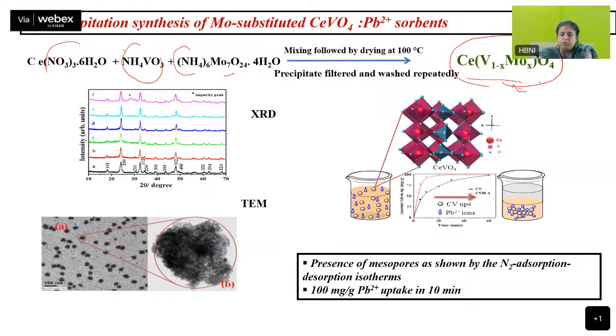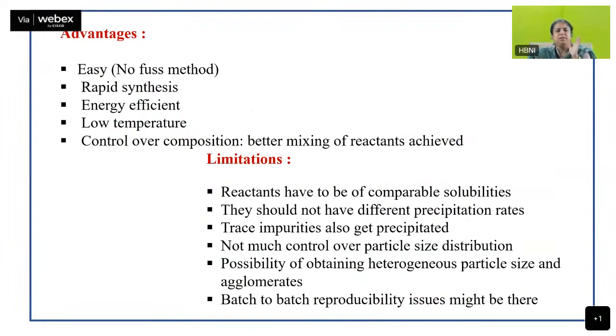And simply without any heating, simply at 100 degrees centigrade, I got this product. And later on, this product was utilized for sorption of toxic metal ions like lead, which showed a very, very impressive lead uptake of 100 milligram per gram in just 10 minutes. Okay. Advantages. It's a very easy, no fuss method at all. You simply have to mix. Okay. Rapid synthesis, energy efficient because you're not heating, low temperature, control over the composition because you don't have to go for a multi-step thing.